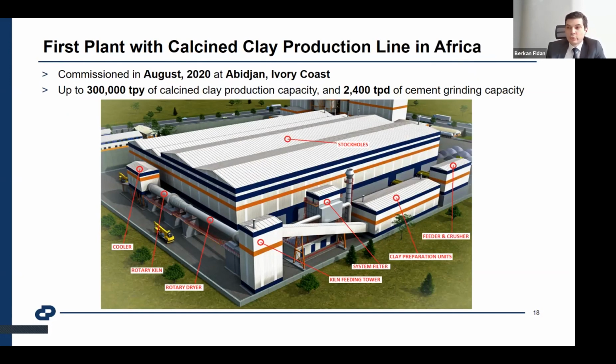I want to introduce to you our first plant in Africa, the first calcined clay plant in Africa also, a fully integrated calcined clay cement grinding plant, and fully greenfield constructed. Commissioned in mid-August this year at Abidjan. The capacity is up to 300,000 tons per year, depending on the composition of the raw clay, its moisture content, and other issues. Its cement grinding capacity is 2,400 tons per day in the plant.